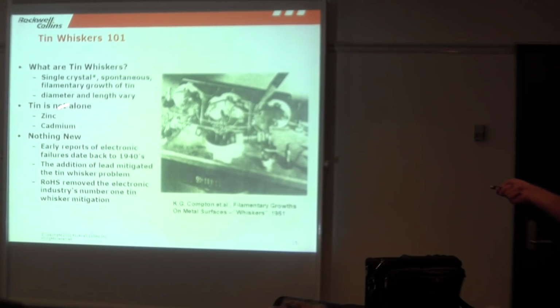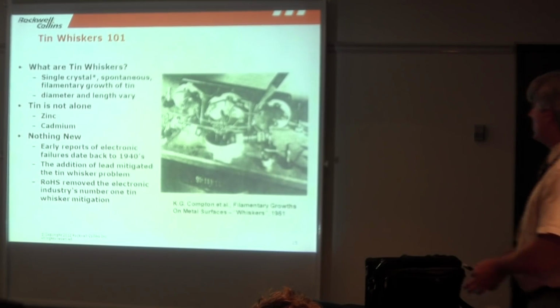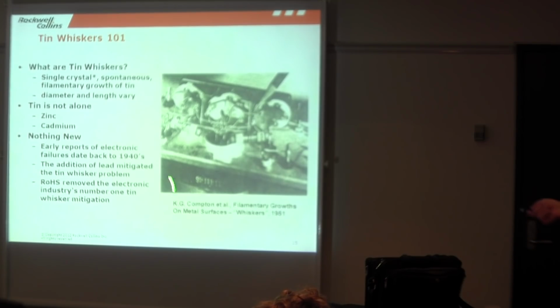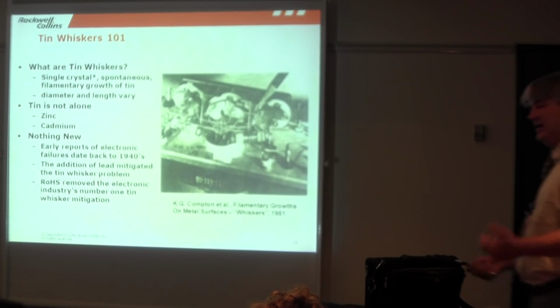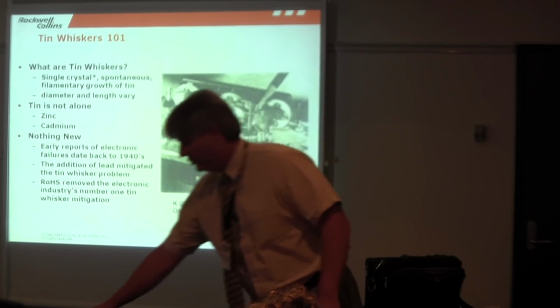They also saw it on zinc and cad. They took a look at it. They said, if you put a little bit of lead in here, it goes away. And oh, by the way, if you use tin lead and you use the eutectic alloy at 183 degrees C, it goes from a liquid to a solid at one temperature, 1 point, like a light switch. You're good, don't worry about it. So we bumbled along for the last 60, 70 years until RoHS came in. We had the technical solution. It's been taken away, so now we have to adjust.